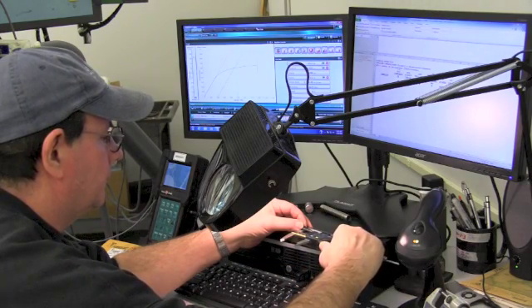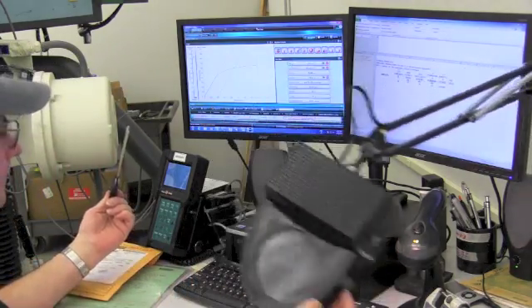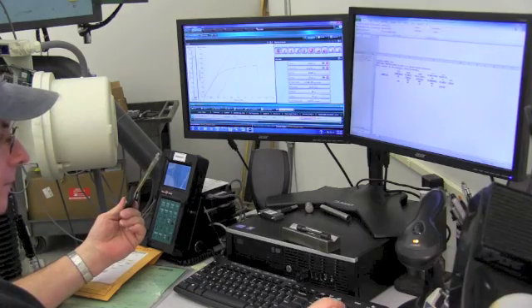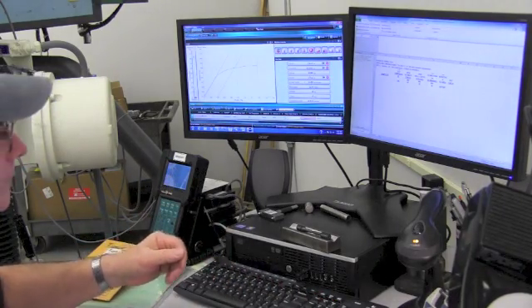The ultimate or highest load recorded and the load at yield are divided by the original cross-sectional area to calculate stress and the results are checked against the customer's requirements.